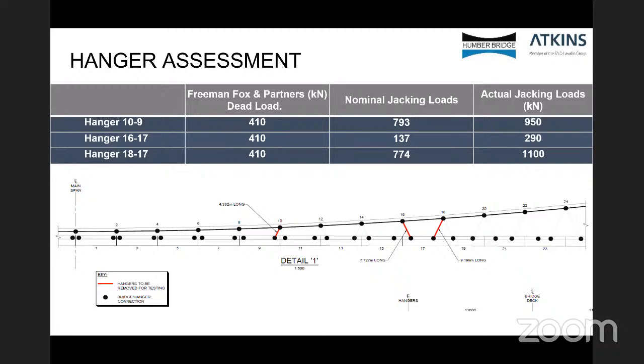This compares the load from Freeman Fox and Partners. For each hanger, they assumed 410 kilonewtons. The nominal jacking load that we determined through analysis was 793 for the first one, and the actual jacking load was 950. Comparing that to hanger 1617, the nominal jacking load that we derived was 137 versus 290. The reason the actual jacking load is slightly higher is because you have to overjack the deck to allow the pins to be released. So what we found is that the nominal load in the hangers aligned with our analysis rather than the original design of the bridge, whereby the hangers should have been equally loaded. So if we look on to the next slide.